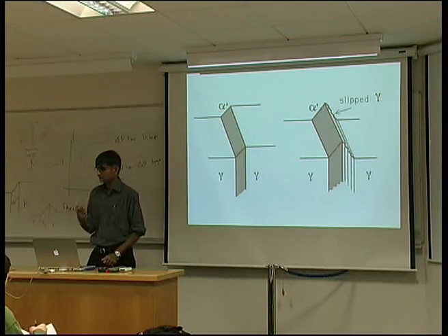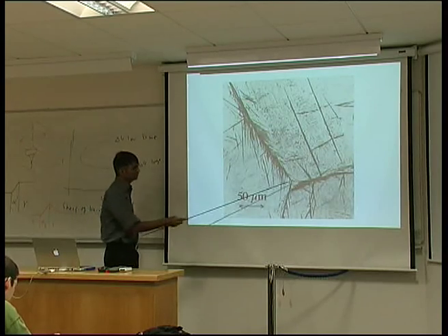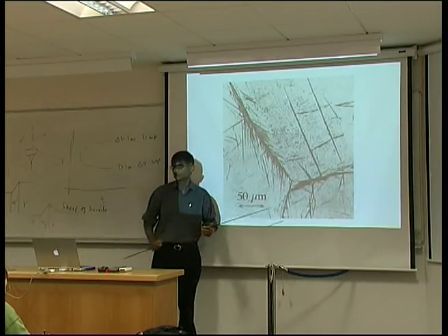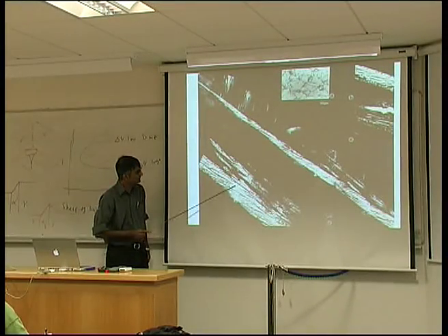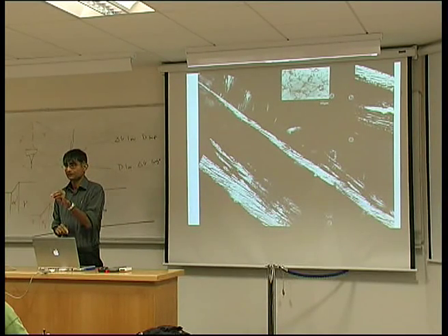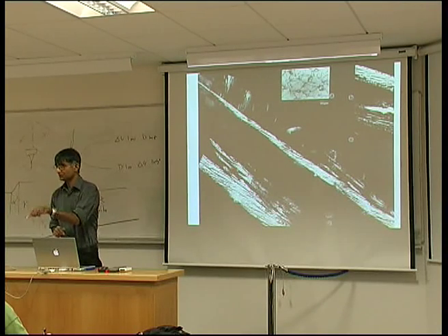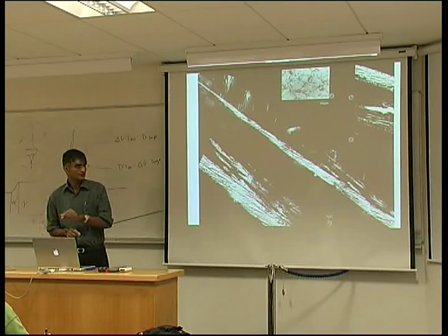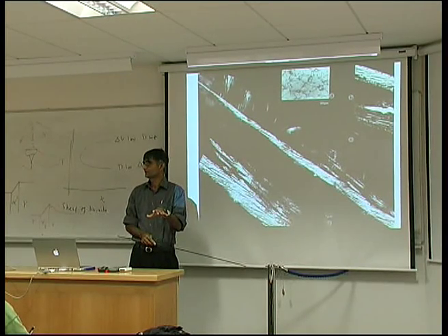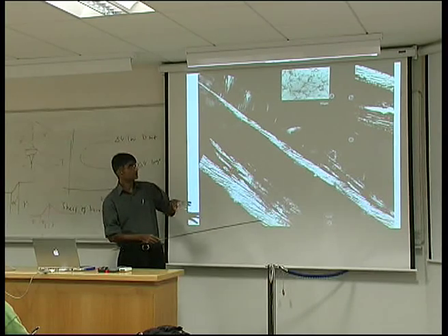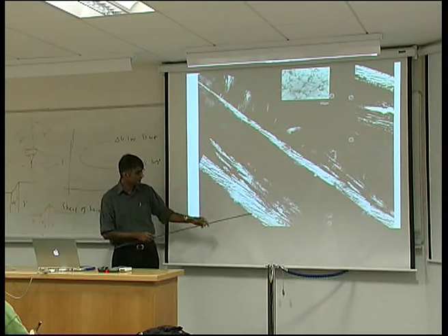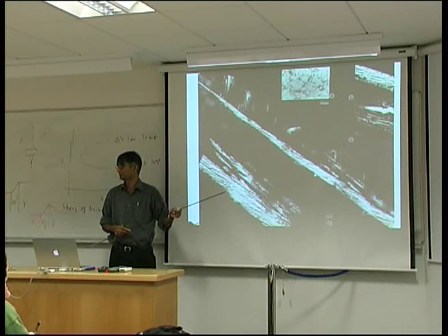And this has a very major consequence on the development of bainite, because what we see optically here is a single platelet of bainite. You can see the scale here. This is an optical micrograph. It actually consists of thousands of tiny platelets of bainite, which grow to a limited size, and then they are killed by that plasticity. The transformation itself causes a shape change, which induces plastic deformation in the austenite, which stops the interface. So each platelet here grows to a size of the order of 10 micrometers and stops. Whereas in the case of the martensite, the plate grows right across the grain boundary. So a martensite plate would be homogeneous and of that size. Here we have to renucleate the plate every time we want to continue the transformation.